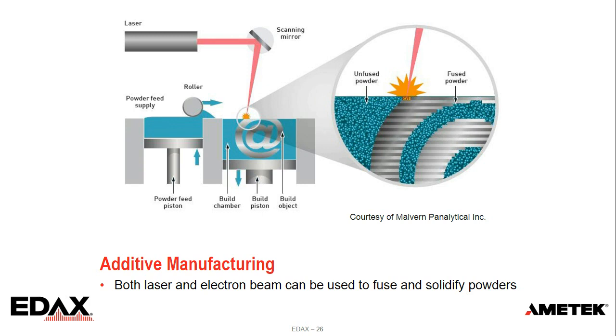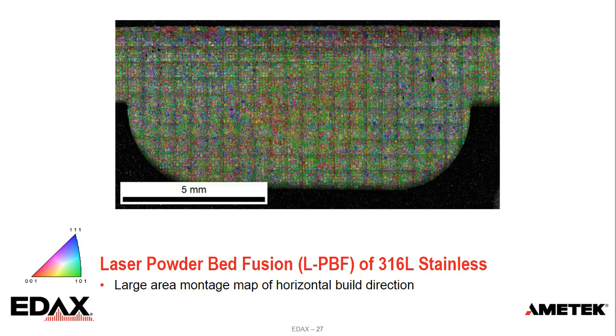And this is just an example using laser powder bed fusion. This is a 316L stainless sample. This shows the orientation map. Again, this is a large-scale montage map, but it's showing what's termed the horizontal build direction. In that case, what it means is that the layers are building up towards us, so we're looking at the very top layer after the fabrication. And you can see there these are the greenish colors. I hope they're green. This is where my color blindness will hurt me, but to me they're a greener color.